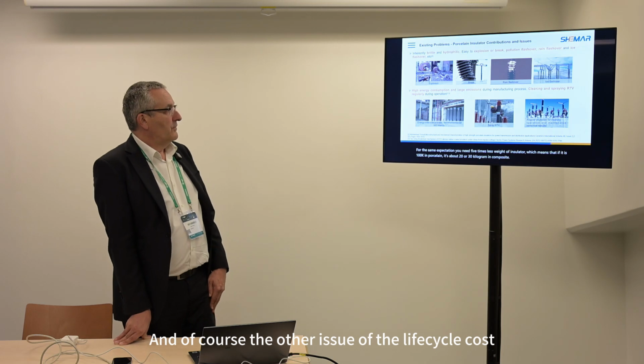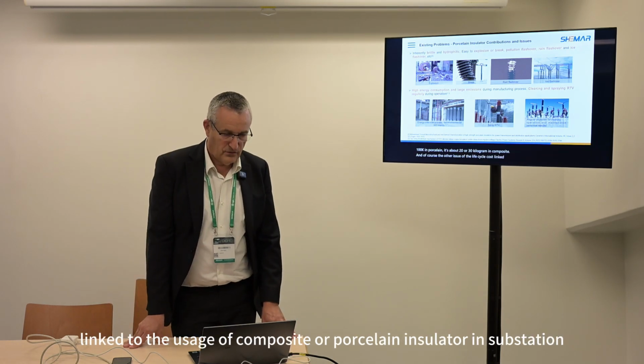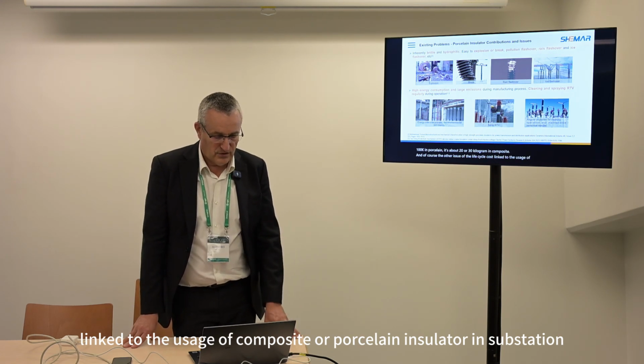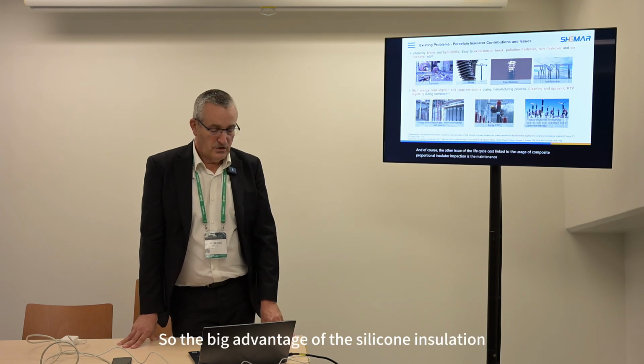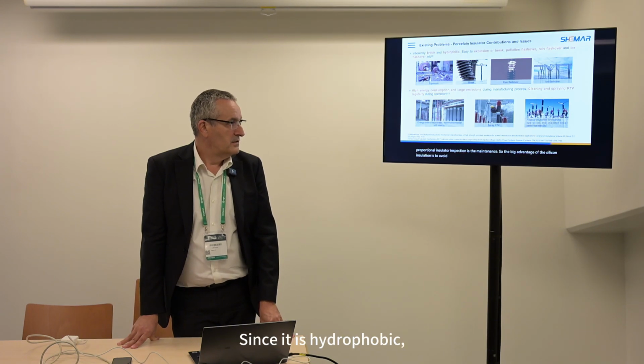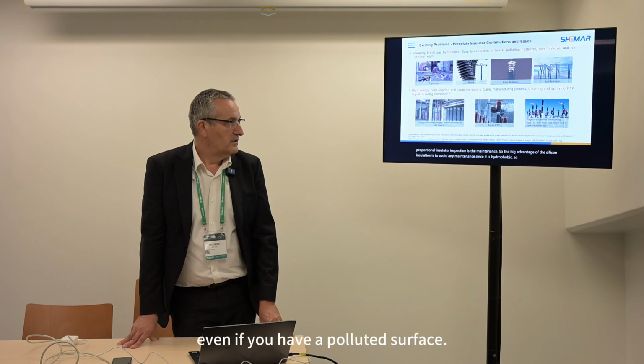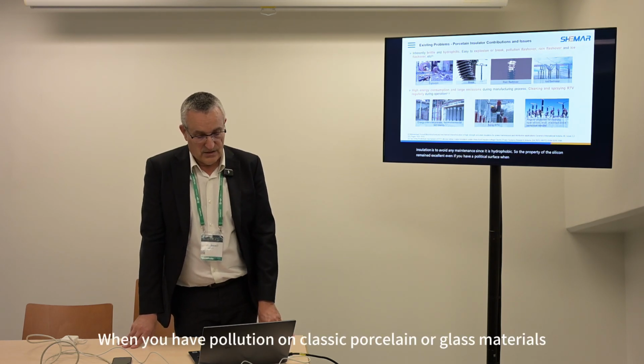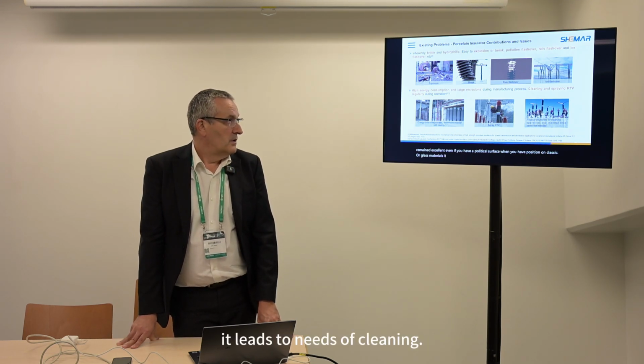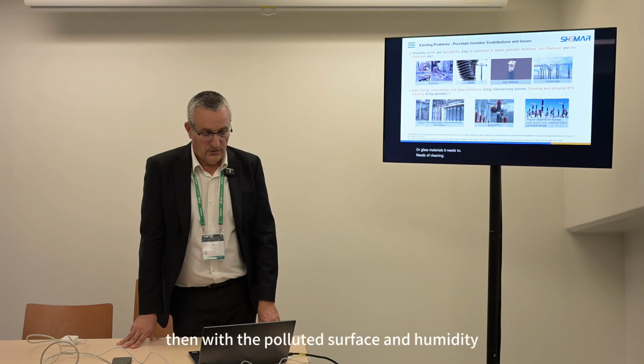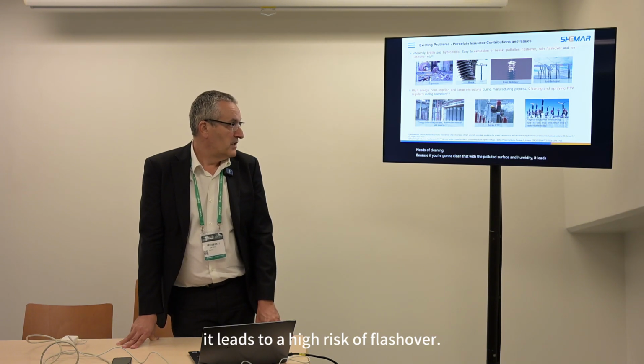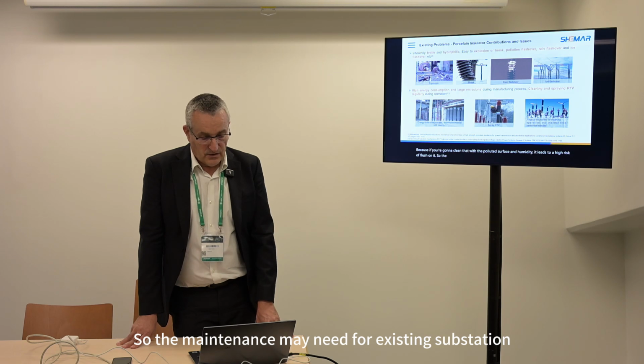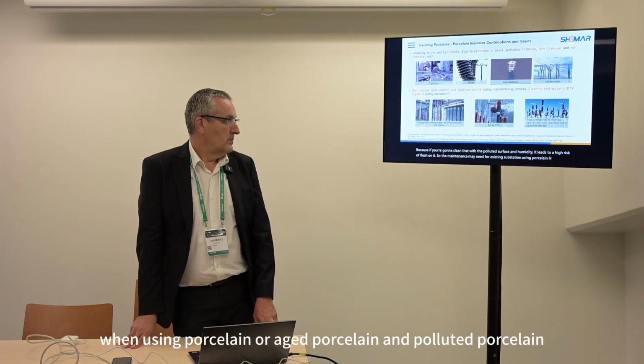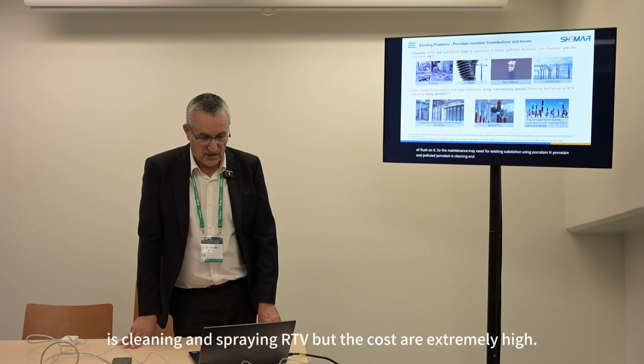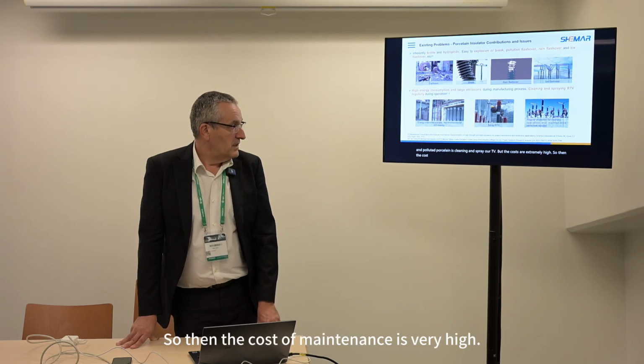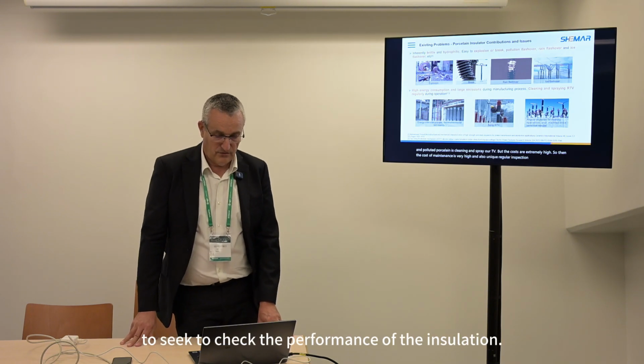And of course, the other issue of the life cycle cost linked to the usage of composite or porcelain insulator in substation is the maintenance. So the big advantage of the silicone insulation is to avoid any maintenance, since it is hydrophobic, so the property of the silicone remains excellent even if you have a polluted surface. When you have pollution on classic porcelain or glass materials, it leads to the need for cleaning, because if you don't clean, then with the polluted surface and humidity, it leads to a high risk of flashover. So the maintenance needed for existing substations using porcelain, or aged porcelain and polluted porcelain, is cleaning and spraying RTV, but the costs are extremely high. So the cost of maintenance is very high, and also you need regular inspection to check the performance of the insulation.